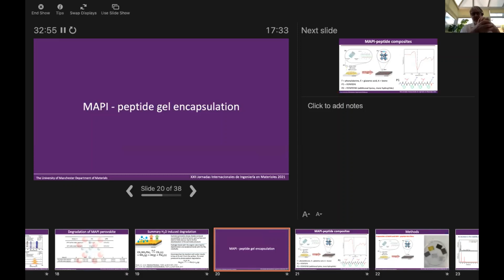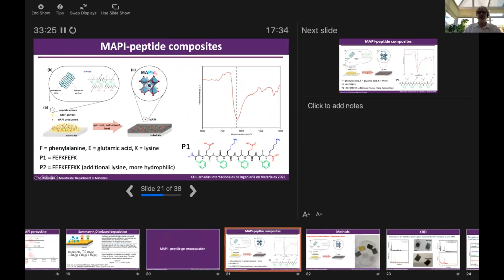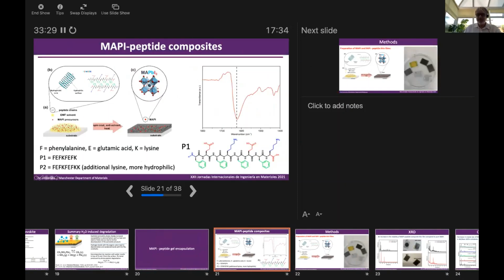But it's very difficult actually to grow MAPI as nanocrystals using traditional techniques. And so most of the approaches that have been used have been to use some kind of encapsulation or a template in which to grow the MAPI. There's been some work using metal organic frameworks where they grow the perovskite in the pores, and they see shifts in the emission. So we thought, partly because we have an excellent biomaterials group in our department who make gels from peptides, why don't we try encapsulating these things with a polymer gel or a peptide gel? And as I said, because we had access to these peptide gels, we started with these.